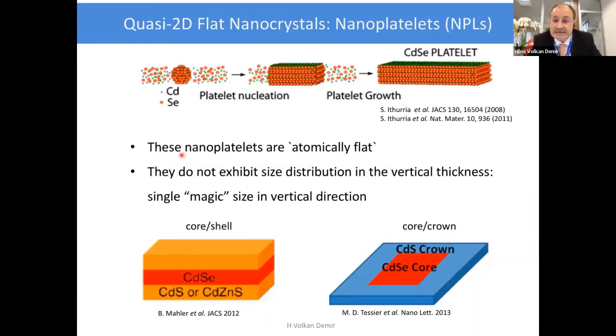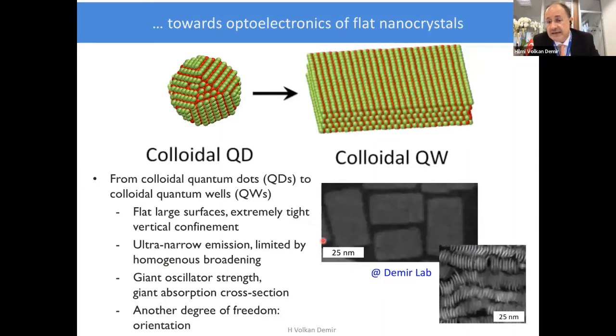And to push the limits, the answer comes from an atomically flat family of nanocrystals, which we call nanoplatelets. The work indeed is inspired from a French group in Paris. What they showed is we can make these very well controlled atomically flat nanocrystals, either just the core structure, or we can do a shell, or literally extend them to make core-crown. And that's what we have been looking at. This is what you see we can do in the lab, either putting them face down or edge up. This is a paradigm shift because this creates extremely large surfaces for us to work with while we keep the vertical quantum confinement tight.